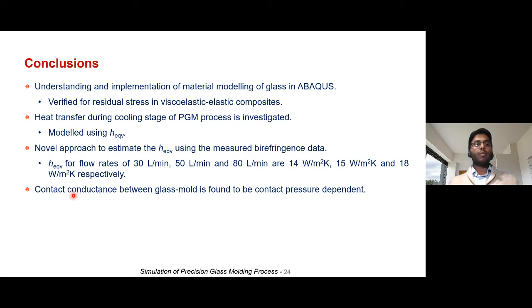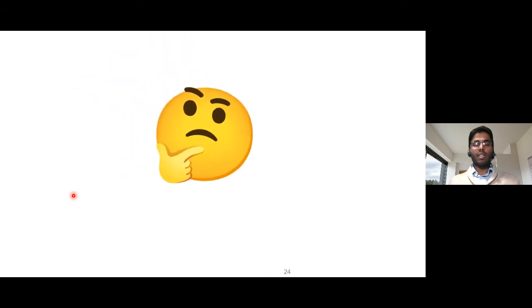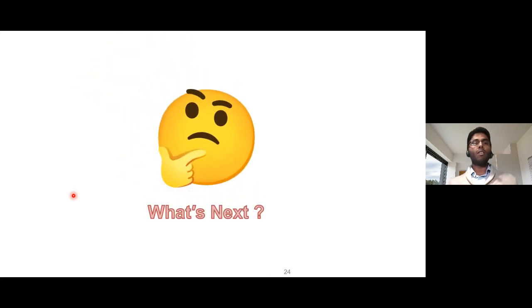And for glass pressing operation, pressure dependent contact conductance has to be specifically used for modeling this simulation. These were the major outcomes we found from our research. Now this is totally fine, this is all we have done. We had gone deep into the issues of the glass molding operation, but the curiosity is what's next actually. Is that all, or is there something beyond this?